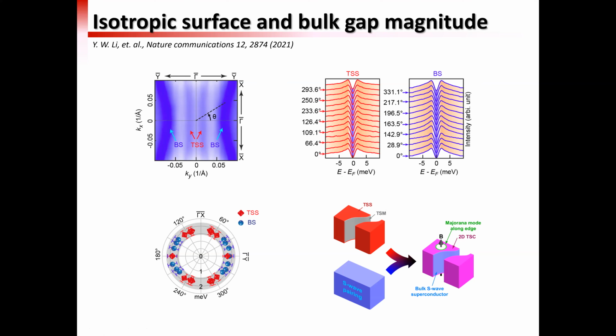So, from the fact that the gap of the surface state and the bulk state opens at relatively the same temperature and also reaches a similar magnitude, we conclude that this topological surface state is gapped by the proximity effect from the bulk superconductivity, and this will lead to the possible formation of a Majorana mode on the surface if we apply a magnetic field on it.